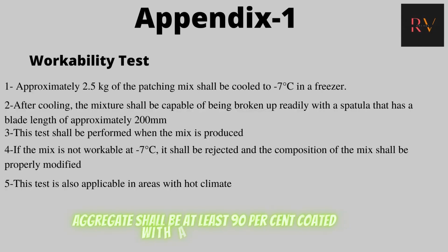Now coming to the last test, which is the workability test. Approximately 2.5 kg of the patching mix shall be cooled to around -7 degrees Celsius in a freezer. After cooling, the mixture shall be capable of being broken up readily with a spatula that has a blade length of approximately 200 mm. This test shall be performed when the mix is produced. If the mix is not workable at -7 degrees Celsius, it shall be rejected and the composition of the mix shall be properly modified. This test is also applicable in areas with hot climate. Aggregate shall be at least 90% coated with the bituminous film in this test.